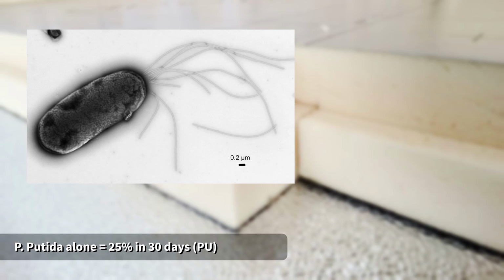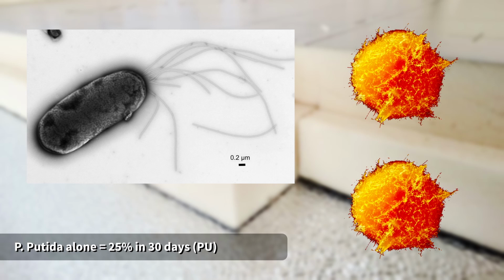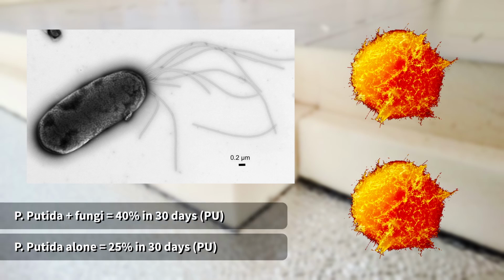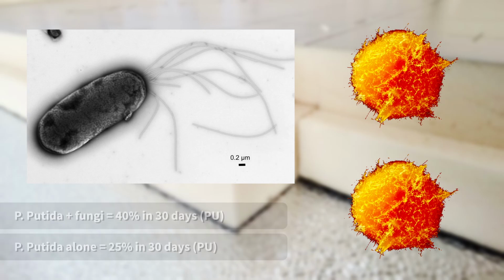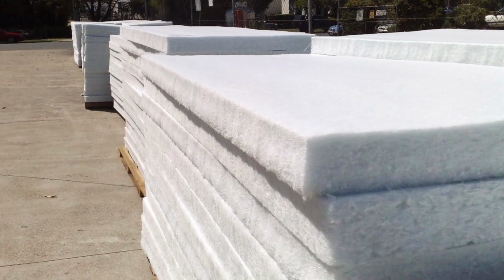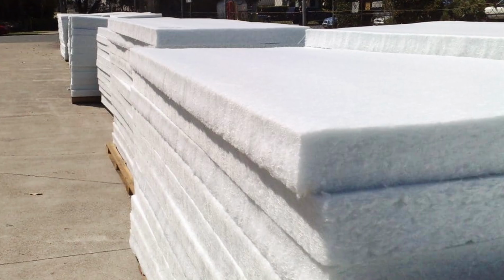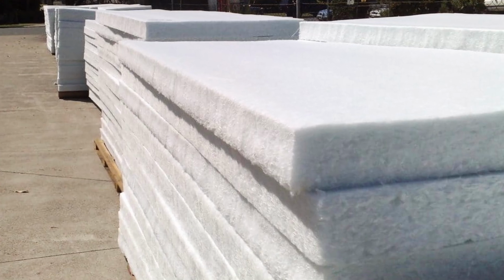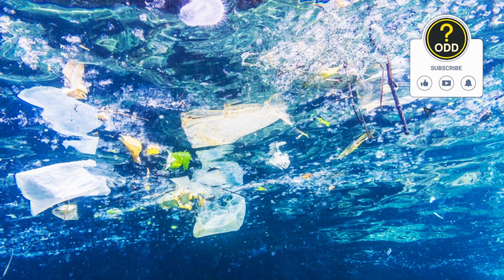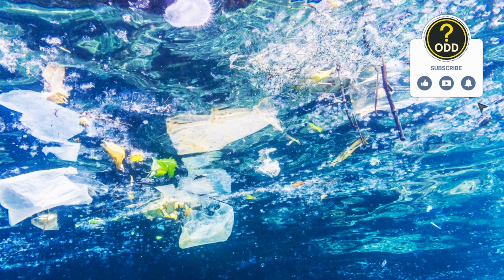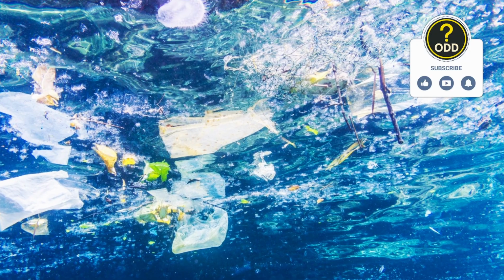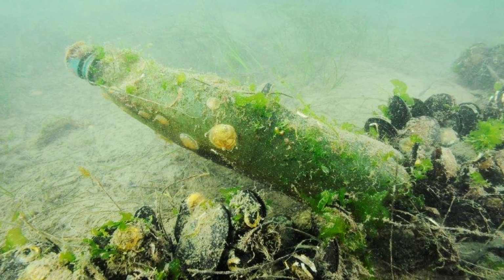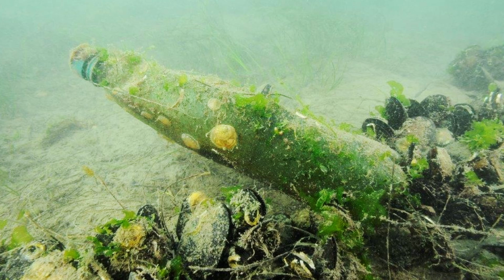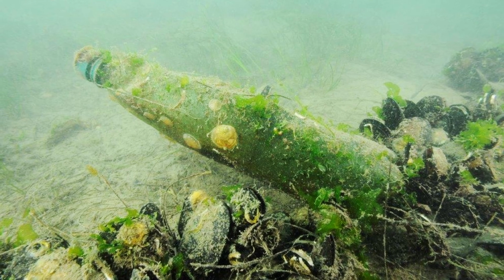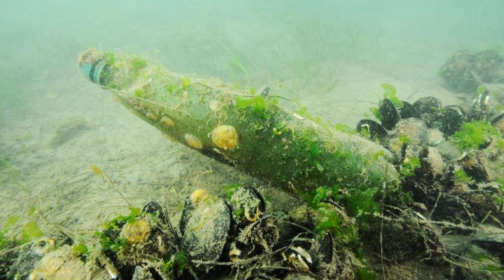But when co-cultured with fungi in conditions similar to those found in plastispheres, degradation increases to as much as 40%. Even polystyrene, one of the most resistant plastics, shows changes when covered by plastisphere biofilms. In tropical marine environments, plastic fragments showed increased oxidation, up to 60% more surface carbonyl groups compared to sterile control samples. These results don't come from isolated enzymes or optimized lab conditions. They come from natural microbial communities working together.